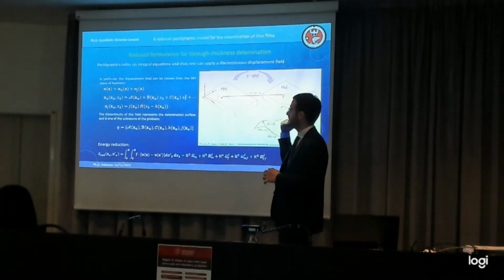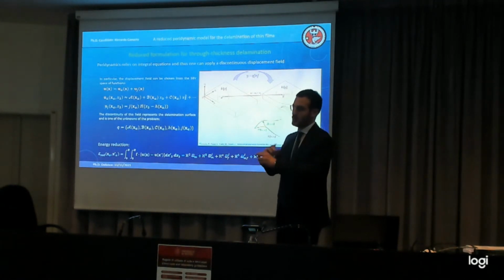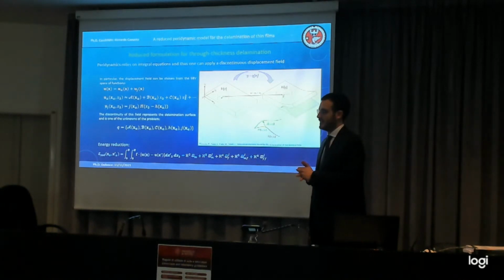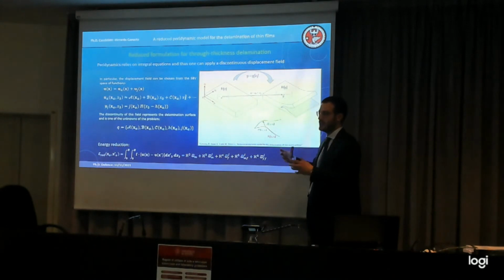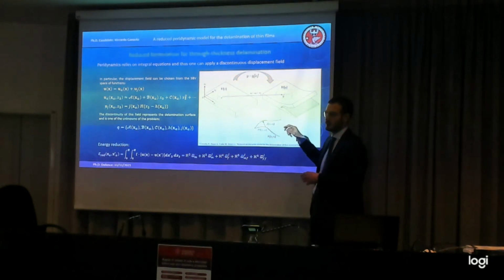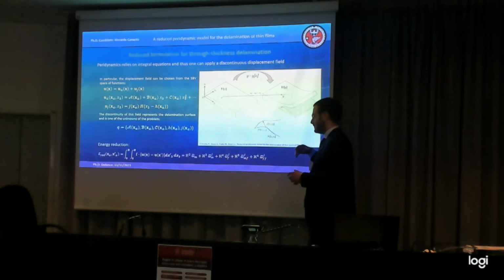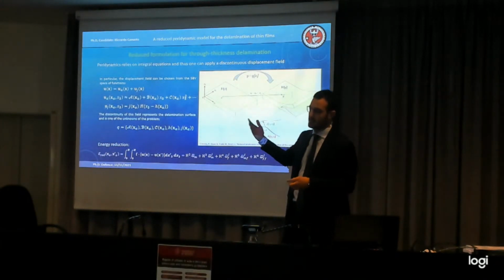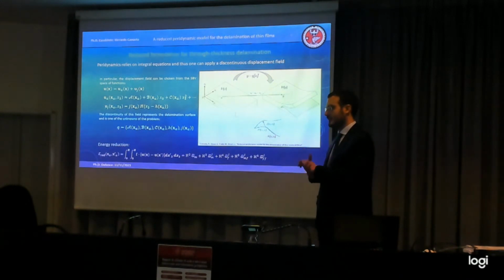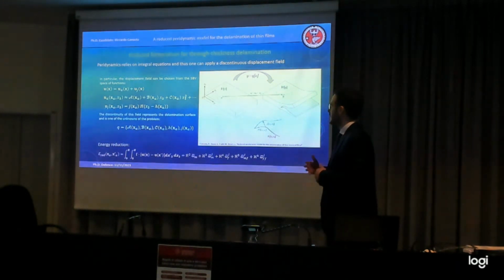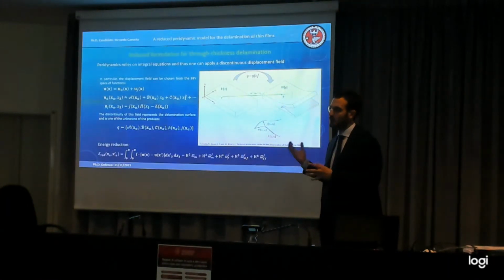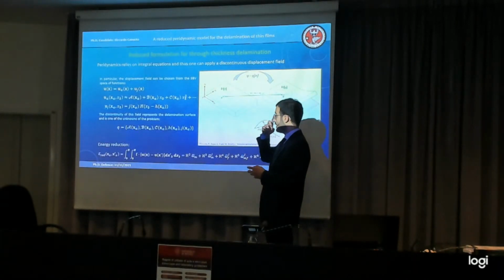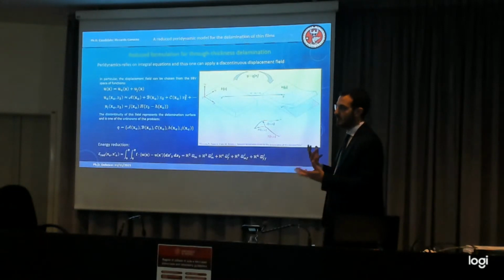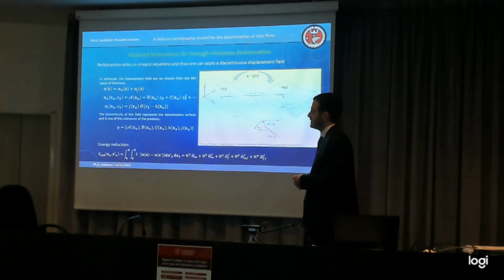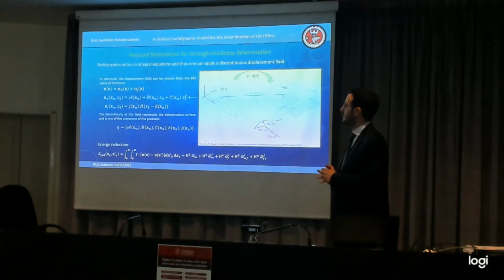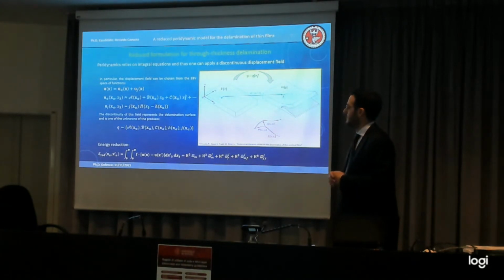I would say that for the phase field case, analytical solutions are also very, very complicated. We've been treating poles, and we were not able to obtain any analytical solution for the strange patterns followed by the cracks at each loading step. They are very strong, but they have a weakness that depends on the fact that you typically need a numerical model to obtain the solution of a specific problem. This is just one of the few cases in which you can obtain something analytical by performing a rather significant approximation. I mean, in a sense, it's an extraction of the type of failure involved. I hope I answered the question.